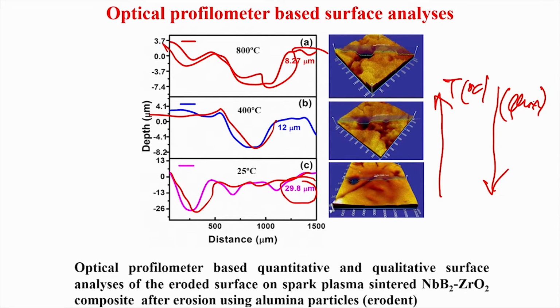So, what it means is that the severity of the erosion damage decreases as you increase the temperature, and this is an extremely important observation, because these ceramics are meant to be used for high temperature applications. If these materials can experience less wear or less erosion damage at high temperature, there is nothing like it, and that is how there is a success in developing this kind of materials, with the expectation that they would experience less wear at higher temperature.